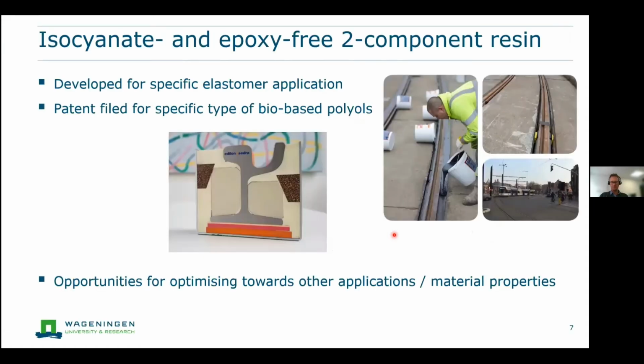What we did was try to look for alternatives for these isocyanate and epoxy systems. And these are usually mixed together and then they react sometimes already at room temperature. So we were looking at a more friendly chemistry that is also reactive at room temperature, but does not use any isocyanates or epoxies. And we succeeded in that for a very specific application, so-called elastomer embedding resins, in which